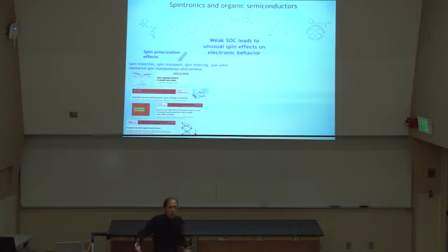And so from that point of view, you would say, well, that's the best group of materials to build spintronics out of. And that's all true. But oftentimes you realize that these materials also have low charge carrier mobilities. And since spin diffusion length is actually governed by mobility and spin relaxation times, you see already what you gain on one side and you lose on the other side. But then of course you can start talking about building materials with weak spin-orbit coupling based on carbon that have high mobilities. And maybe then you can essentially get these advantages from two sides.